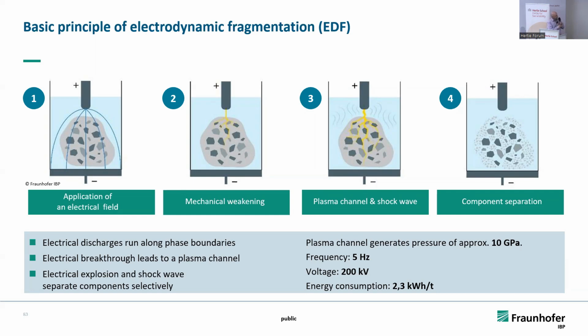We put the concrete underwater between 2 electrodes, and we apply a high electrical field in the range of 200,000 volts. And then immediately, we call them streamers, some lightning discharges run through your composite material along phase boundaries. This leads to a mechanical weakening of your product. And the first lightning strike, which reaches the counter electrode, generates a plasma channel.